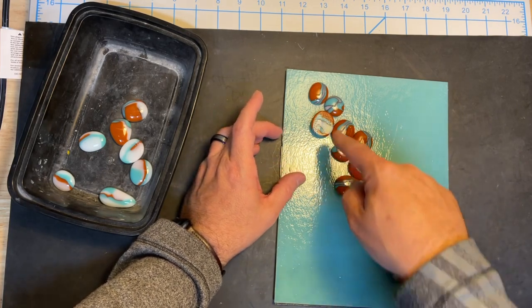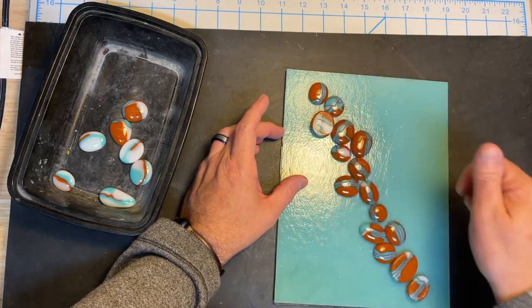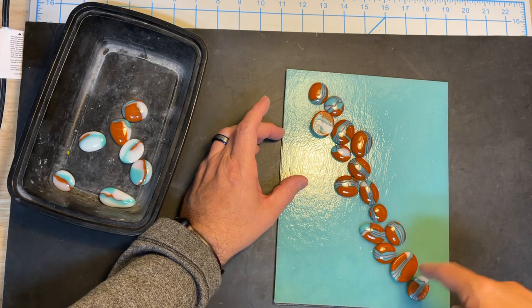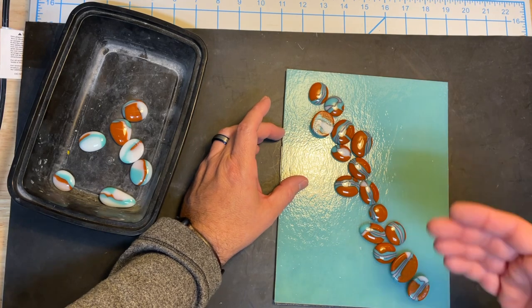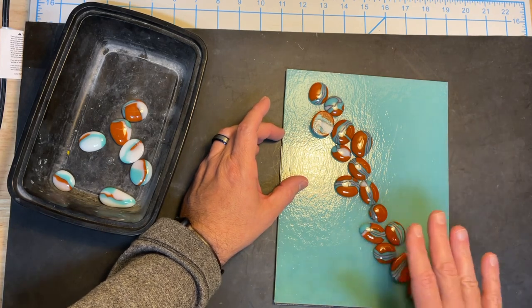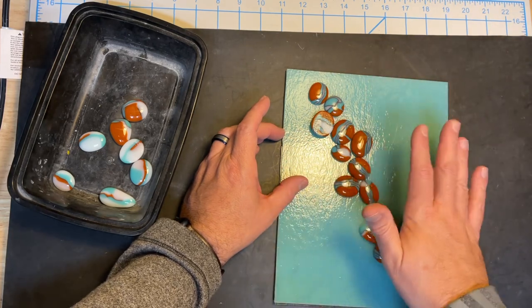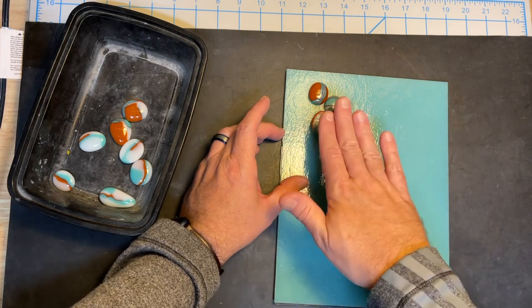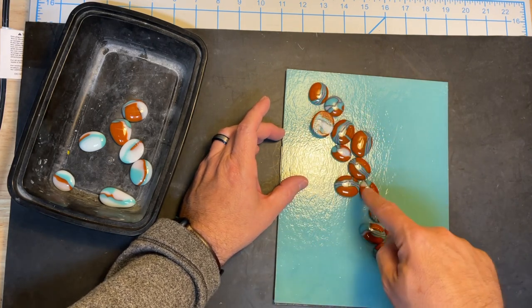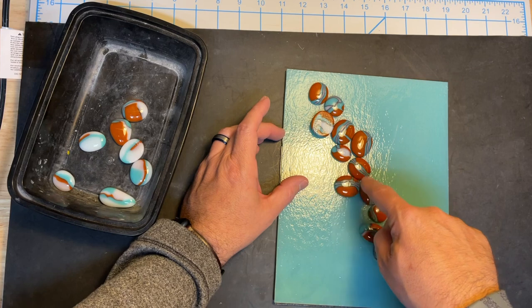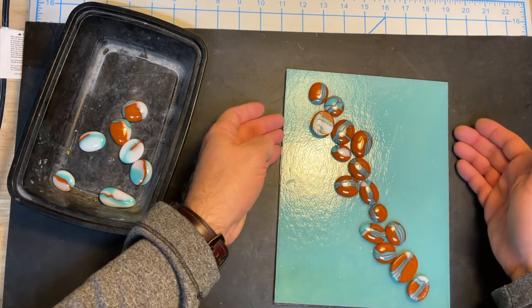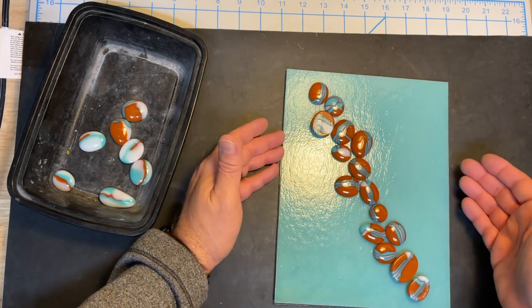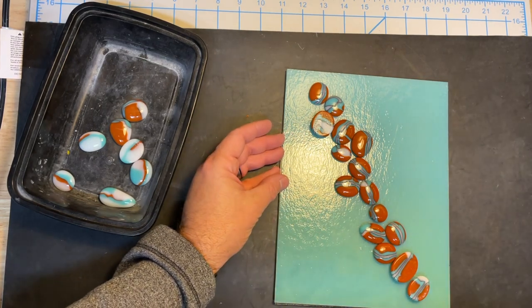What can happen, or what I've experienced with these puddles, is you can get a fair amount of devitrification depending on the glass used and how many times it's been fired. I'm going in knowing that I may have to do another dusting of clear powder after this is done and fire it again to get rid of some of that. You could try to do some powder on this now, but I think the powder wouldn't give you full coverage—you're going to have edges and circles and halos. I'd almost rather just do it as another firing later. I'll arrange this on my kiln shelf and do a full fire on that.